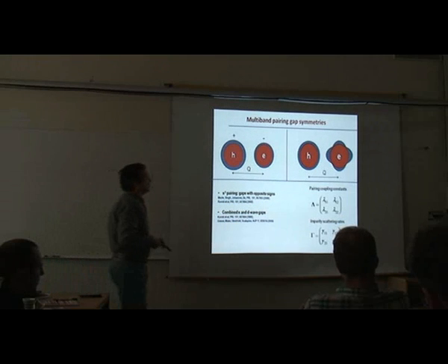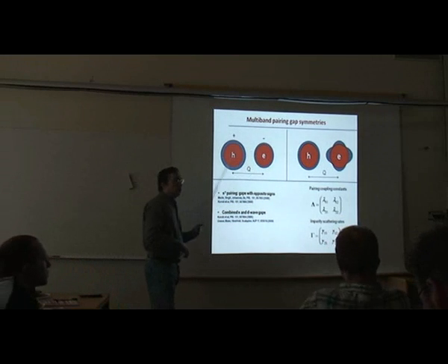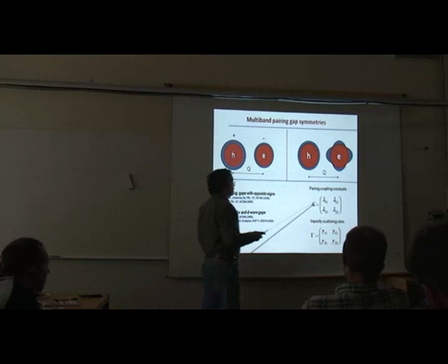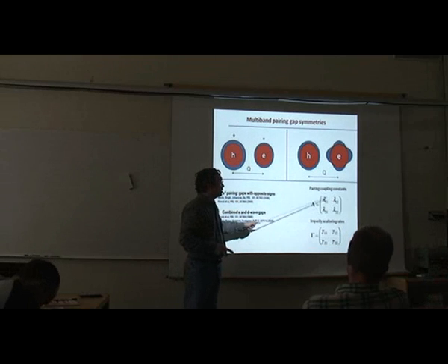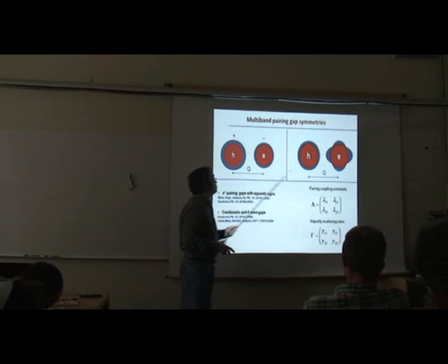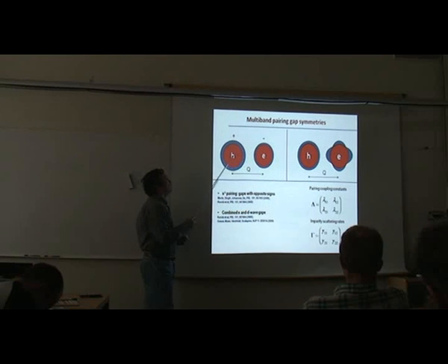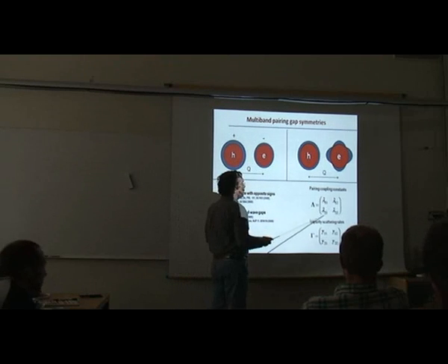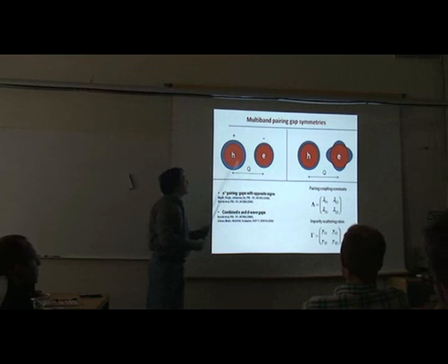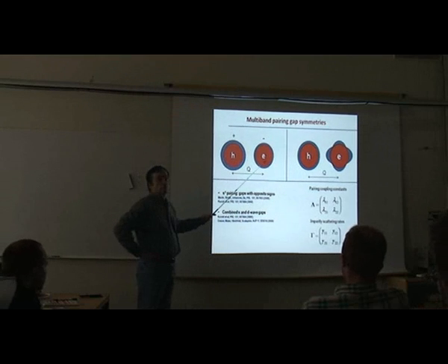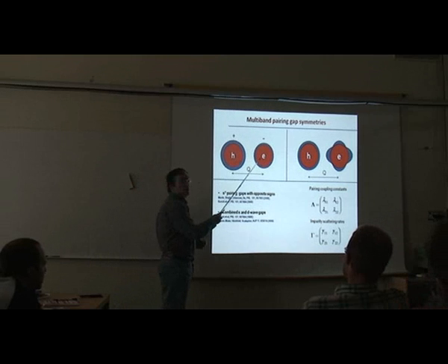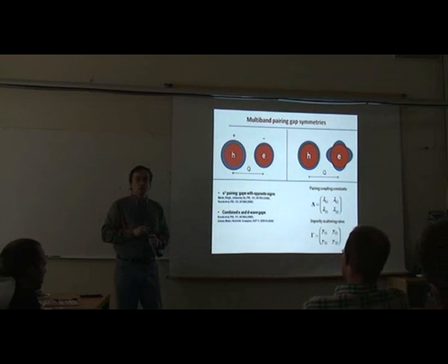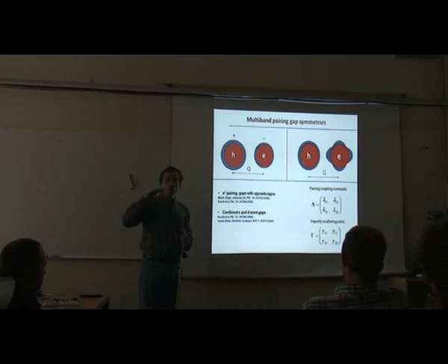So, okay, let's forget about all these complications and consider the simplest two-band model, in which case you have Cooper pairing in two channels. You have diagonal coupling constants which describe the Cooper instability in each of them. And then you have interband coupling constants, off-diagonal, which actually couple this order parameter with this order parameter. All Cooper pairs have zero total momentum, so there is no Cooper pair which consists of an electron here and an electron here. That would have non-zero momentum, which has high energy. So it's all conventional Q equals 0 Cooper pairs.